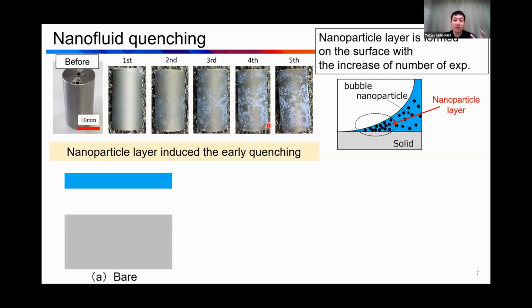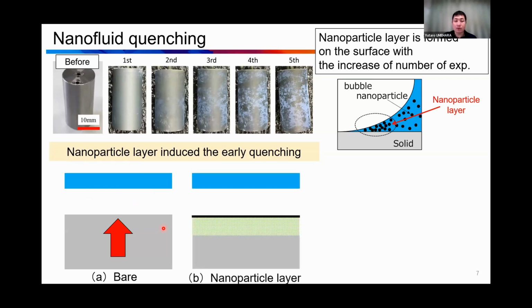In a bare surface case, during film boiling, sometimes liquid-solid contact occurs, but the heat coming from the inside of the high temperature surface causes liquid boiling, and then the vapor film comes back. But when we apply the nanoparticle layer on the surface, liquid-solid contact occurs, but the heat doesn't come so much because the nanoparticle layer has a low thermal conductivity. So the liquid-solid contact is longer than in the bare surface cases. Finally, the small bubbles or pinpoints collapse.